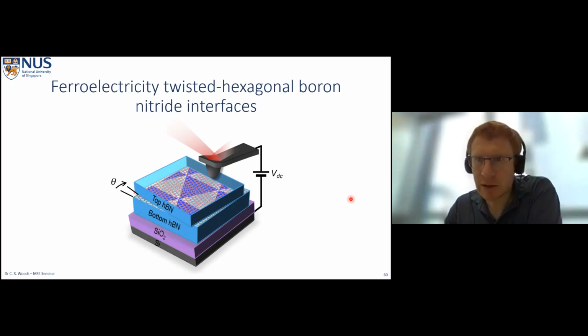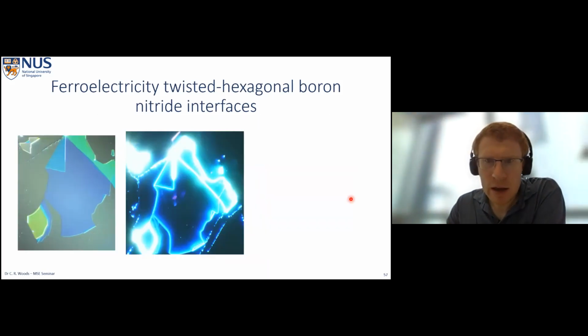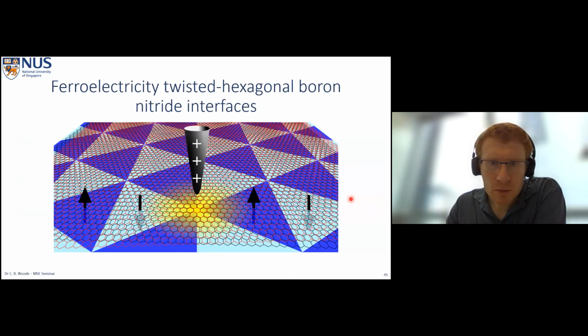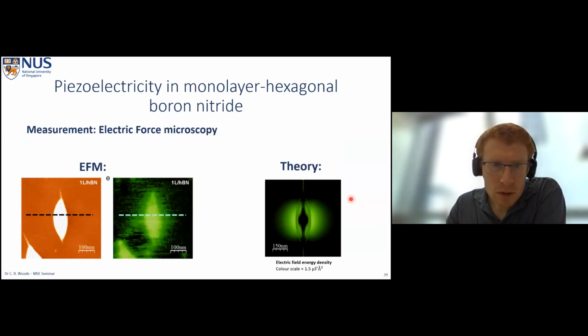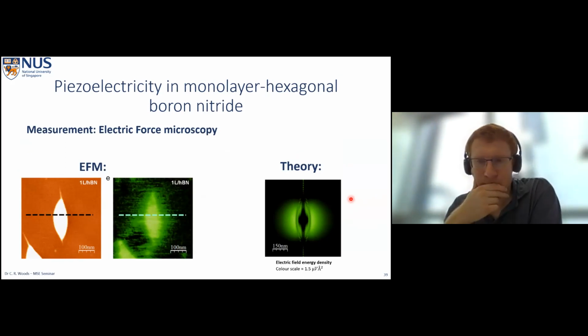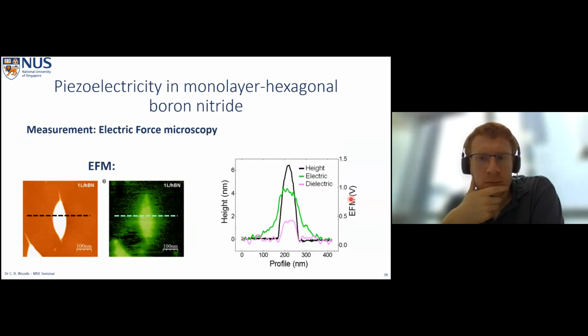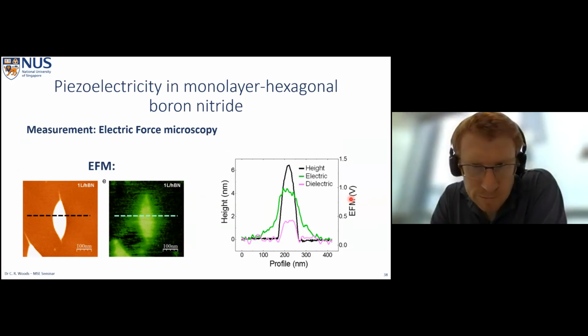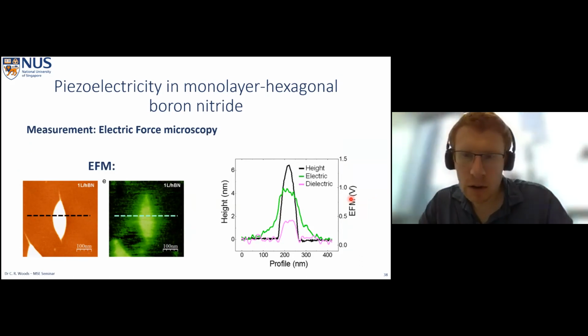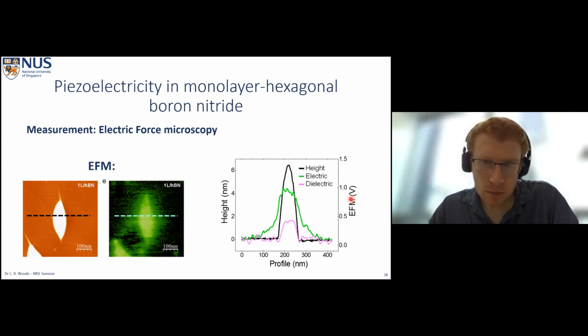Do you mean the piezoelectric stuff? Yes. Okay. Even for zinc oxide and some other materials, you can measure a very good piezo phase loop, even the phase change, phase contrast, right? Just due to some charge injection, also the surface electrostatic effects. So how do we exclude this to confirm that it is really a ferroelectric property?